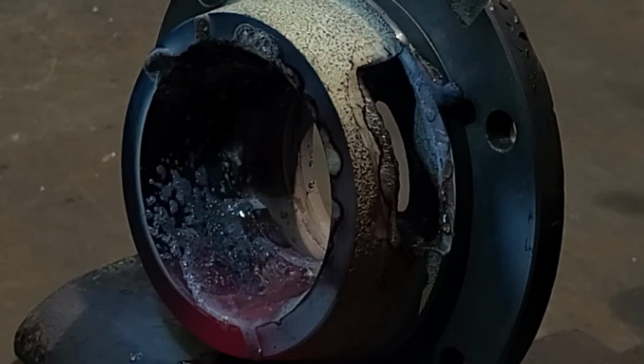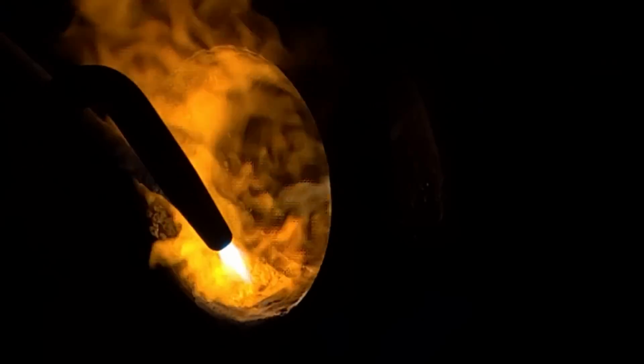Now you see some of those little, I don't know if it showed up good or not, there were little bubbles under the surface. And that was because the iron underneath was cold. That bubble was showing where the rod had not connected with it. So what I was doing was pushing the puddle back a little bit with the flame so that I could get the iron hot and get it to flow out and stick.